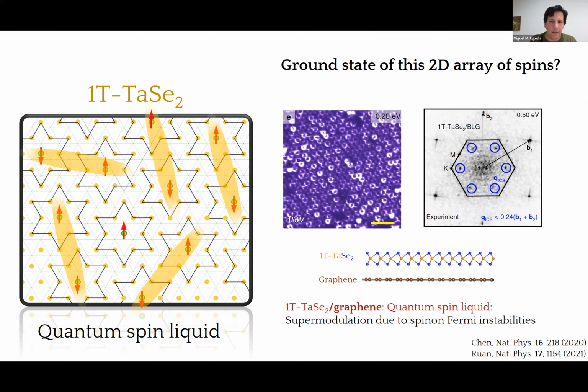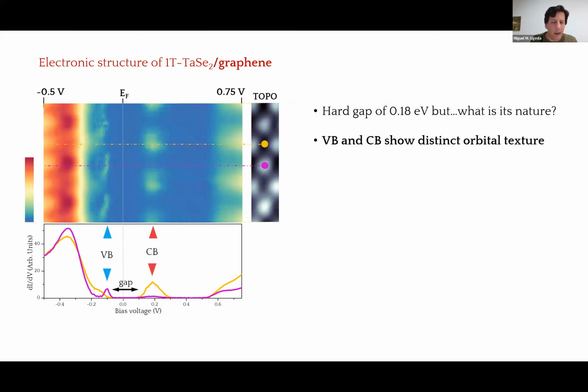So in our opinion, this proposal is very interesting, although it has some fundamental problems, and the reason is because we have also done spectroscopy on tantalum diselenide when it's grown on graphene. So the key point here is the graphene. Here I show you a color-scaled set of dI/dV curves along this path. We go through 1, 2, and 3 Stars of David from here to here, and you can see that the system shows a hard gap.